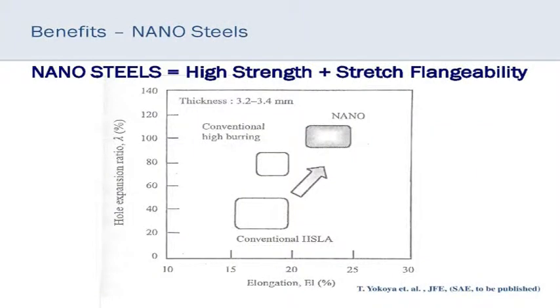So you can see that you'll go from elongation to hole expansion, which is a test where you put a ram through a hole and it expands, and we're very concerned with cracking along the edge of the hole. But with these nanoparticles, you can get very high hole expansion, so you can make those intricate forms without fracture. And that's happening in research and development now.